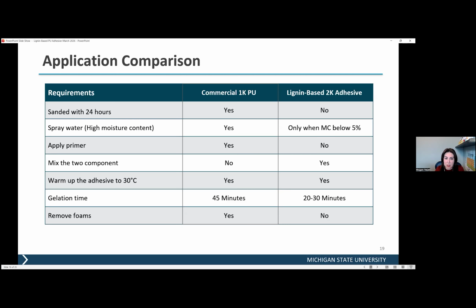Gelation time or open time is the time you have before the adhesives become gels, when you open up the adhesives or mix them together, and you need to apply. For the commercial one component adhesives, we measured the gelation time at around 45 minutes. It could be a different formulation that has a higher open time. And for our adhesives, we have something around 20 to 30 minutes open time.